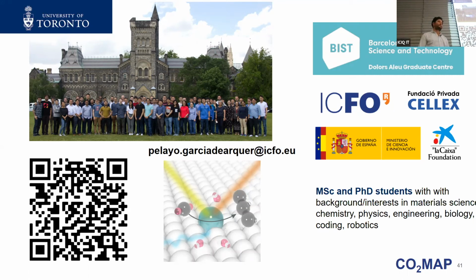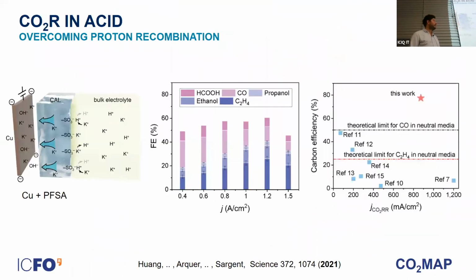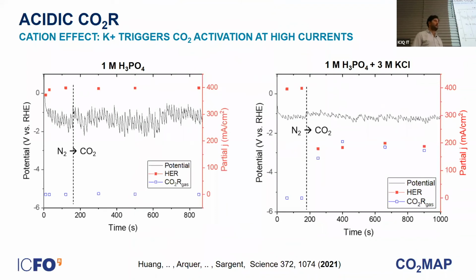Okay, thank you so much for this very brilliant talk. I really enjoyed it. My question is on the cation effect, because if I understood properly, you say that at lower than a threshold of current density, the cation effect was not that prominent. So could you see CO2 reduction without cations at such low current density? And in case you could see it, what would be the triggering effect? Is it the proton source that varies from protons to water? This result is very nice. I was a bit surprised about the result at low current density.